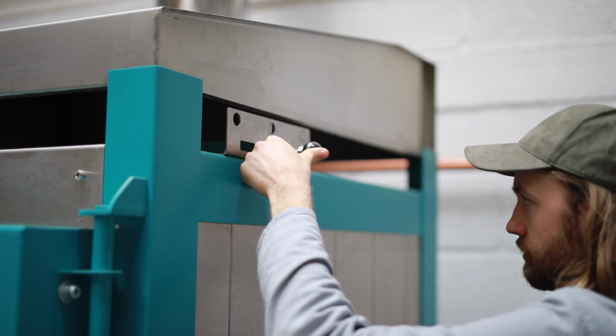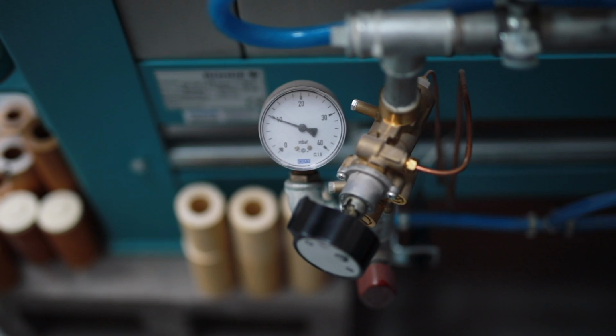For the first couple of hours I keep my burners relatively low. You want to slowly creep up the temperature as you fire. Once my digital pyrometer reads 860 degrees, I set the kiln into reduction. I do this by sliding the dampers over the flue halfway. I then increase the gas pressure to 10 mbar, and I increase my air pressure to 0.42 bar.